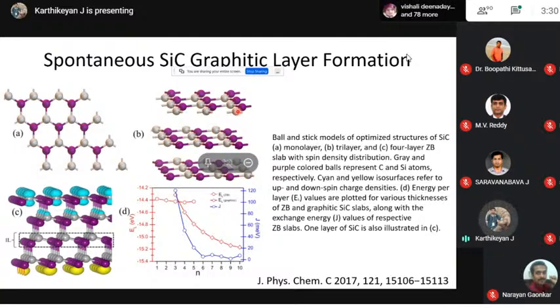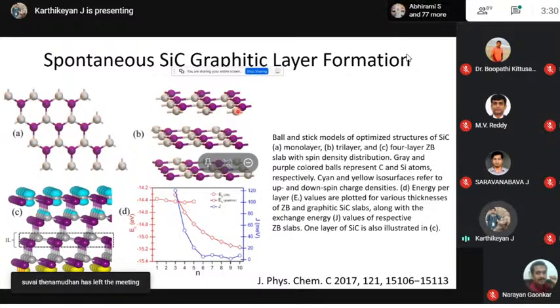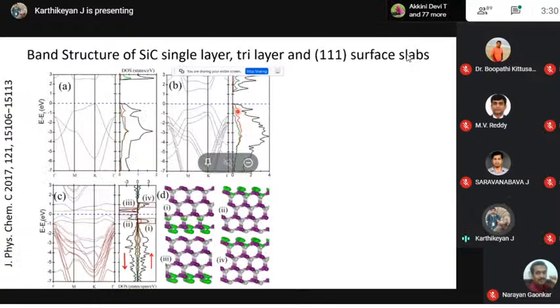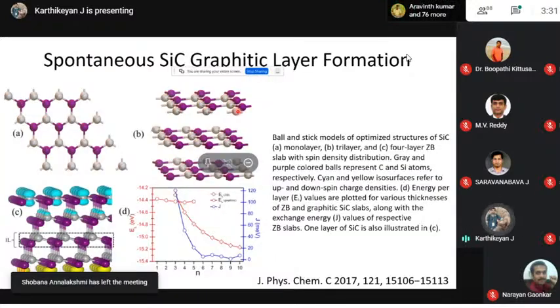So for these graphitic silicon carbides, we started searching papers in this direction. Then we found people had already reported this. Silicon carbide and zinc oxide and many such zinc blende structures form this kind of graphitic structure. Then our idea was to exploit or study this formation of graphitic structure when you add lithium. That was a very interesting observation, so we started studying lithiation in these silicon carbide nanoslabs.